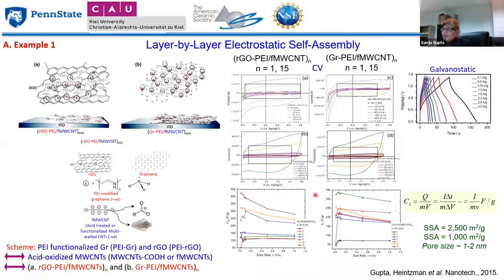And we went all the way from one layer to 15 layers, so 1, 3, 5, and so forth. I'm just showing you as an example only one layer and 15 layers. Interestingly, we determined the storage capacity using this simple formula, which is basically charge per voltage. Then we apply different scan rates and determine our capacity, which is plotted in the bottom two graphs for both graphene and reduced graphene oxide. Depending upon the number of layers, it's not necessarily true that increasing the number of layers increases the capacity. For the classic graphene, with increasing the number of layers we did observe an increase in the capacity, plotted as a function of scan rate, which then starts to decrease, and that's anticipated. Unlike for the reduced graphene oxide with multiwalled nanotubes, where we observed the storage capacity was maximum around 4 to 6 layers.